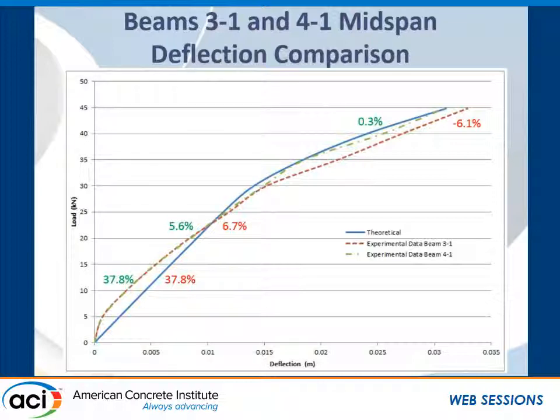Predicted deflections for the beams from the 2013 tests were also consistent with experimental results up to the ultimate load. I think we saw maximum discrepancies of 29% at service load levels and 23% at ultimate loads. At small loads, all beams were stiffer than predicted, and we expect that was most likely related to the accuracy with which first crack load was calculated.